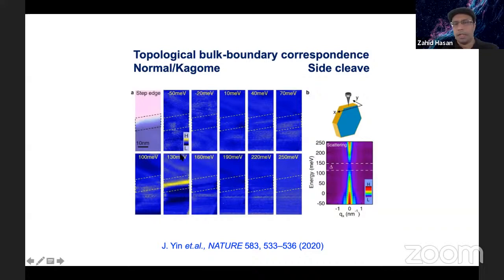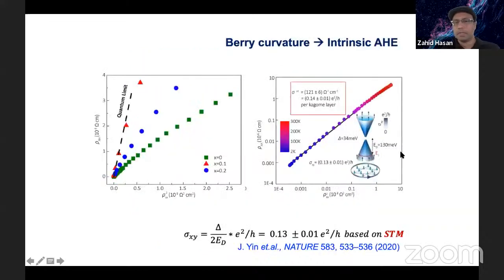So only inside the Chern gap, or the massive Dirac fermion gap, you have this edge state. And with STM QPI, we know that this is dissipationless, backscattering-free. So this is a chiral edge state. We also checked that on a side cleave, this does not appear. So the side cleave is gapped. So this is quite remarkable.